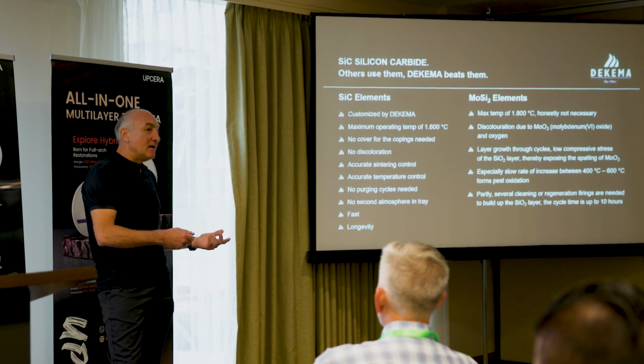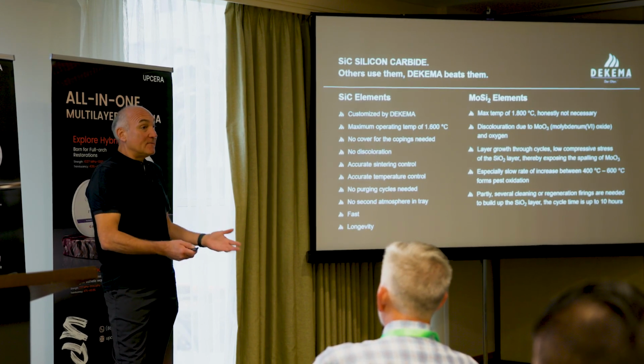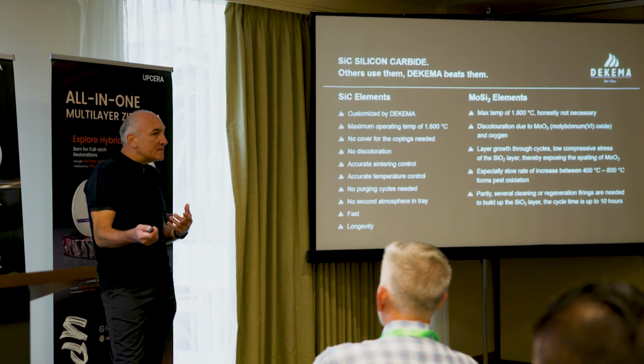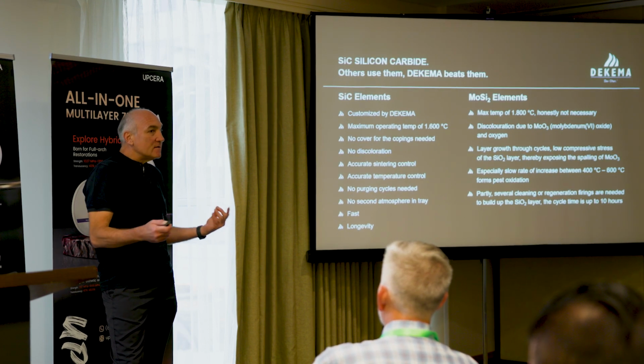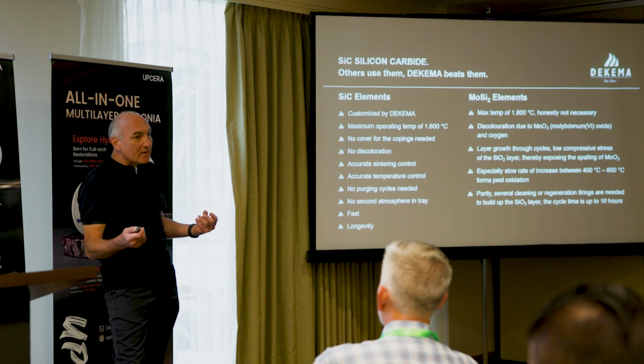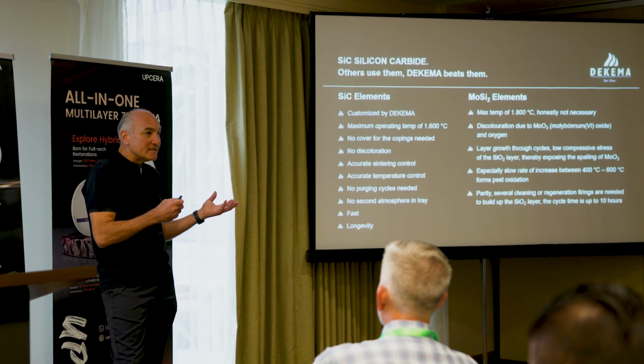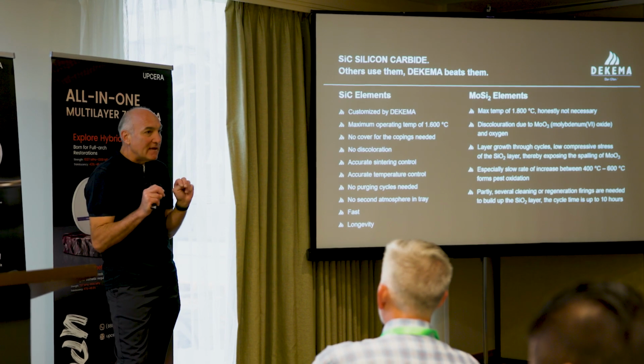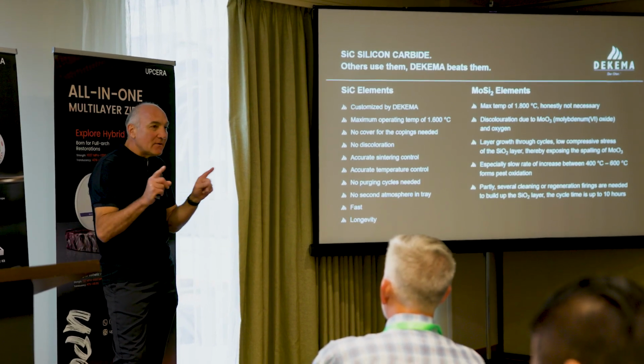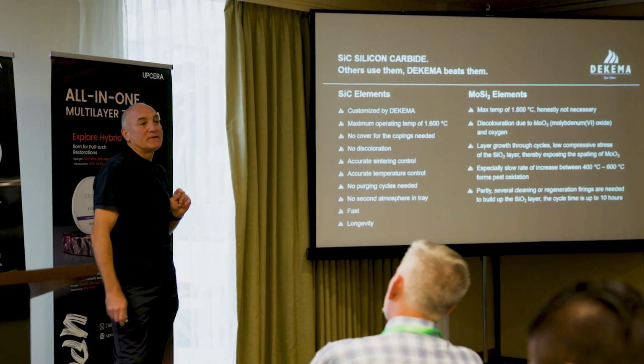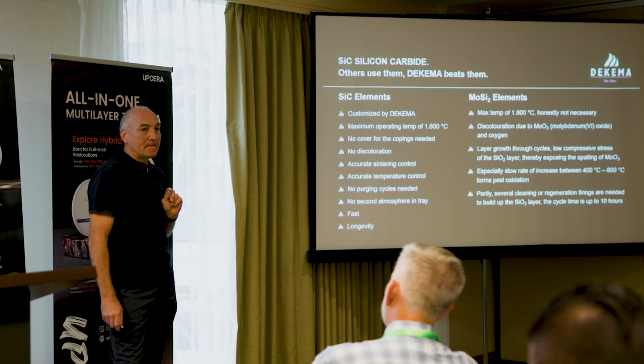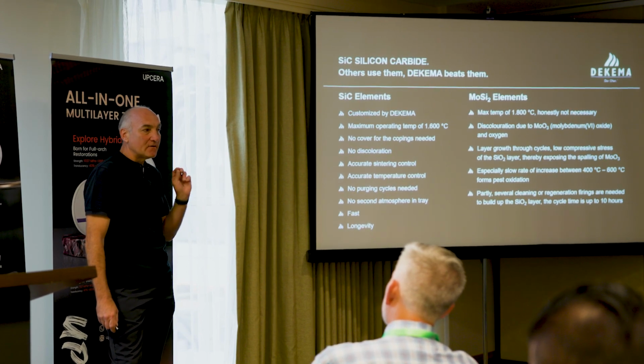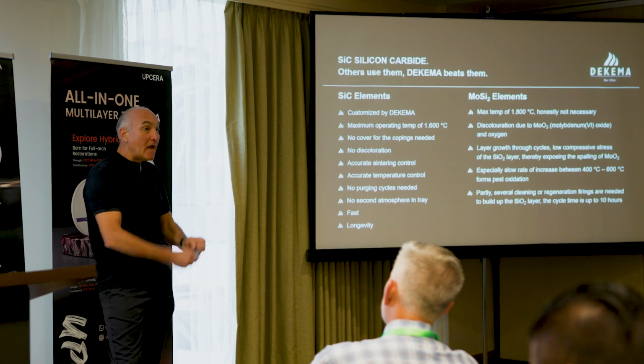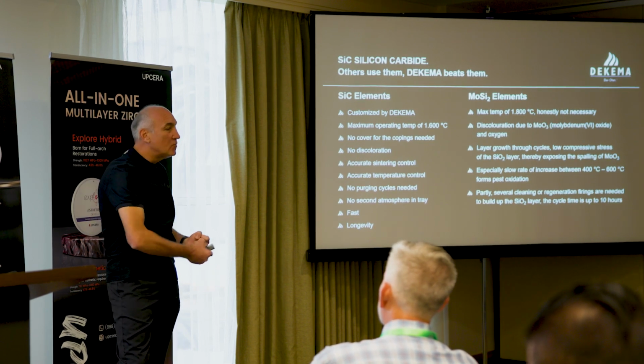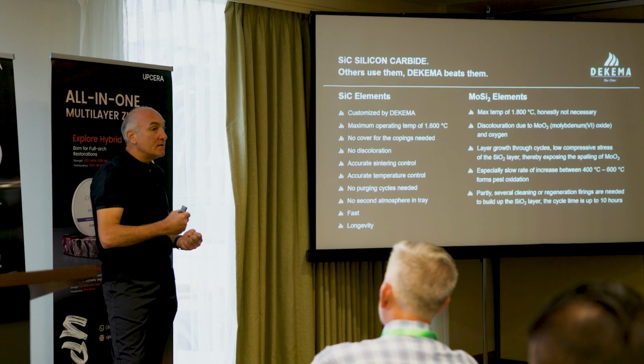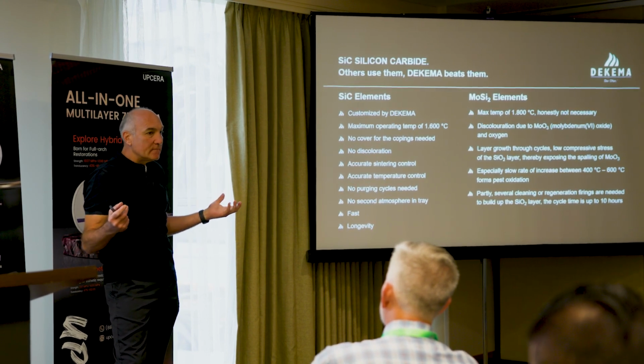Now, as people, since 10 years, especially in Korea, drive 90-minute cycles with a DEKEMA furnace, this goes down to only 3,000 hours. And it looks like these heating elements are not as strong as MoSi. But it's not about this, it's about this number of cycles which we drive. So please remember, it's about the number of cycles you're running, how often do you heat up the heating element and cool it down, and not about how long you heat it.